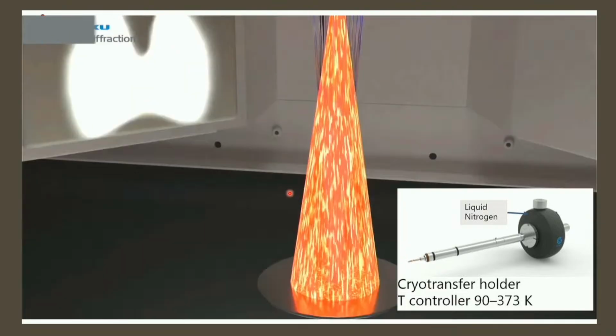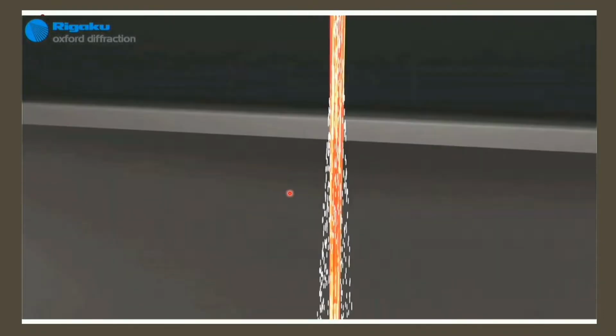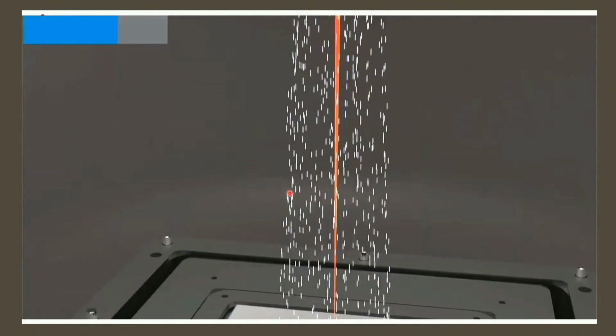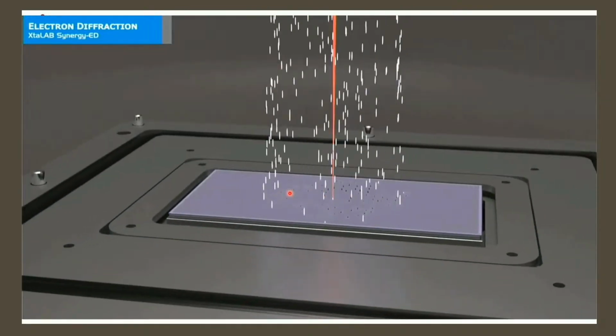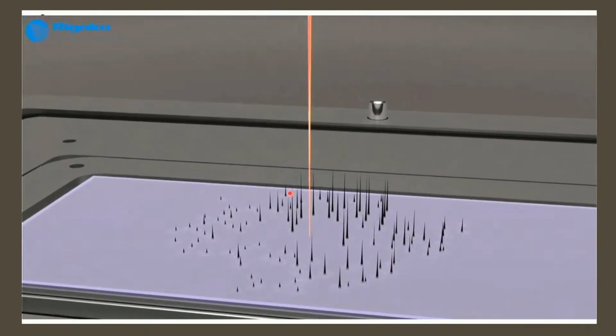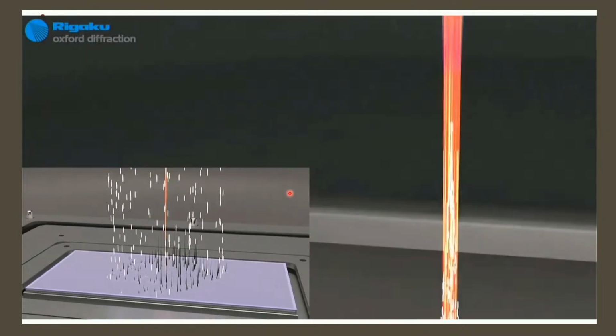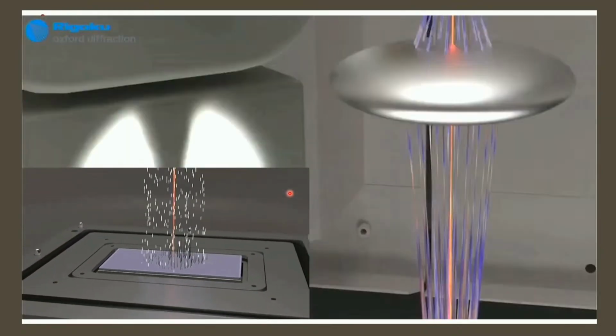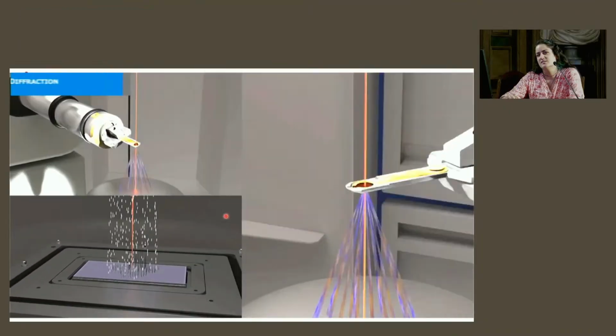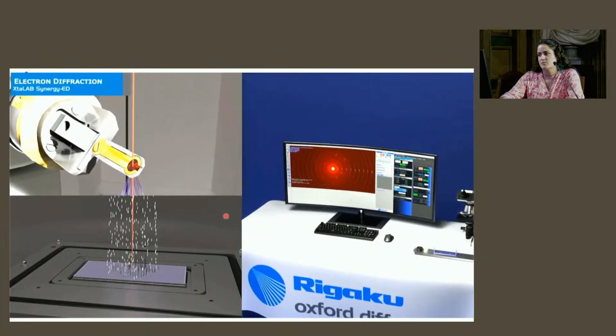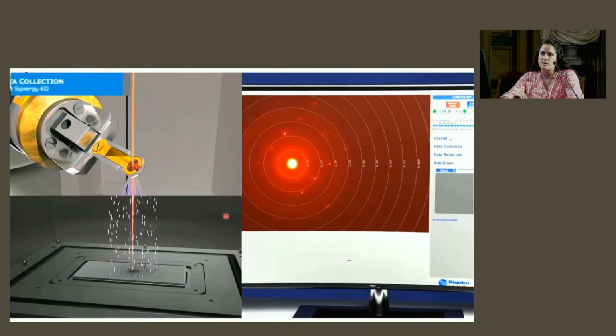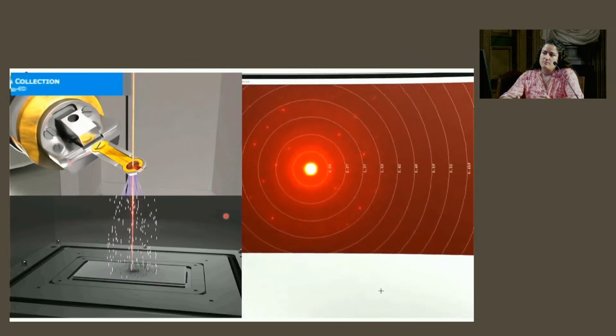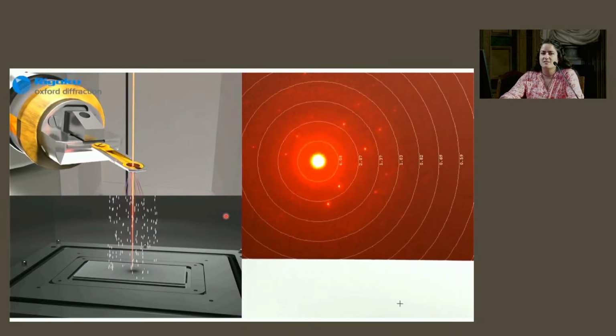Here we have the diffracted beams around our transmitted beam, and this diffraction pattern can be collected very rapidly with the new generation of hybrid pixel detectors, which can collect even a single electron that is scattered by our sample. So we need just a weak illumination to have a large data set of diffraction patterns.